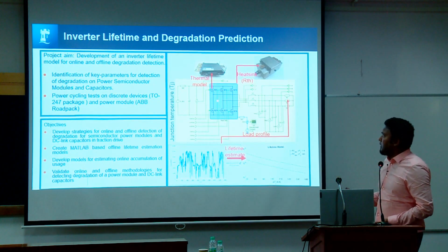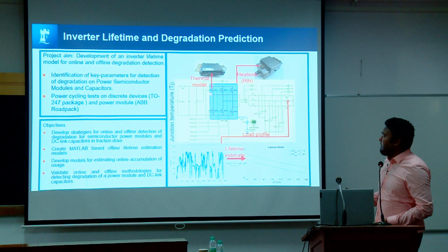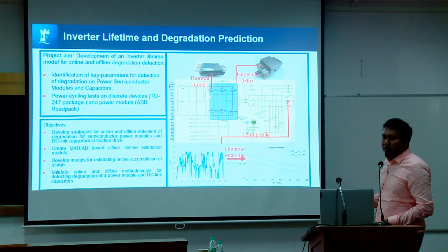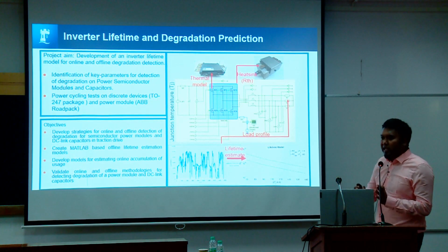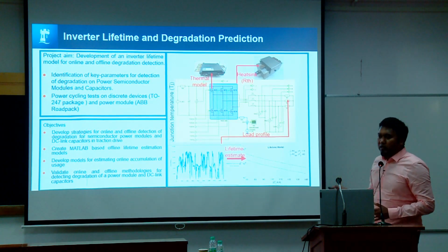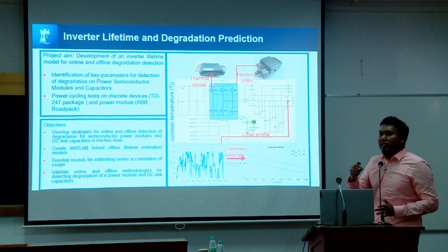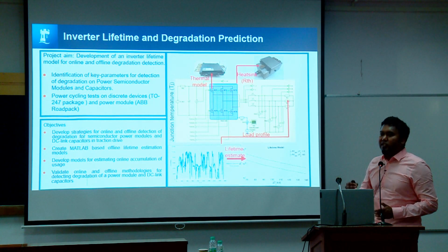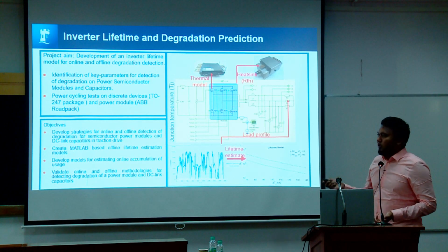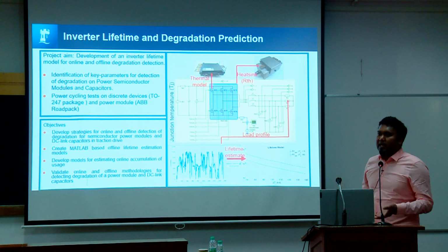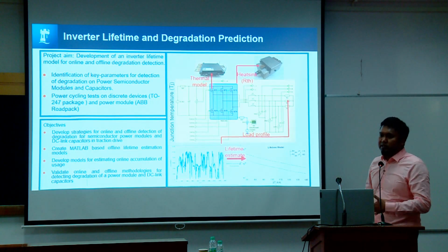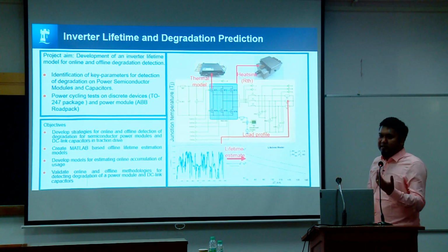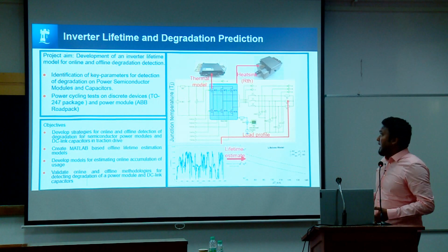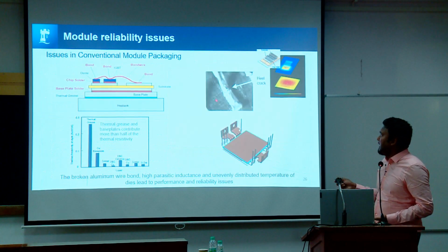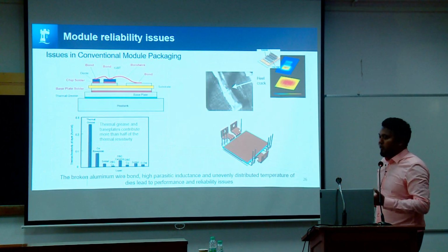For online models, we need to measure the device RDS on or threshold voltage, because what we have seen is that as we age these modules over time, we can see changes in the RDS on and in the threshold voltage. Silicon carbide MOSFETs still have some gate oxide reliability issues, so as the device ages, you can see some impact on the threshold voltage. And when you have this kind of heel crack, this will have an impact on the RDS on.